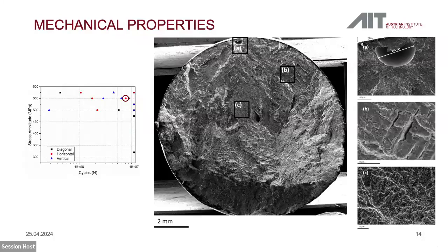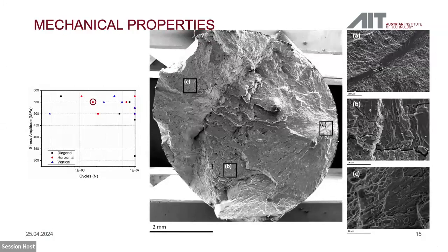This one corresponds to the spot over here. It has quite a long cycle duration, but effectively it had a pore close to the surface with above 200 micrometers diameter. And if you look at the next one, this had a lifetime like 1/5 of the other at the same stress level. And the defect that we found was 1/10 in size.